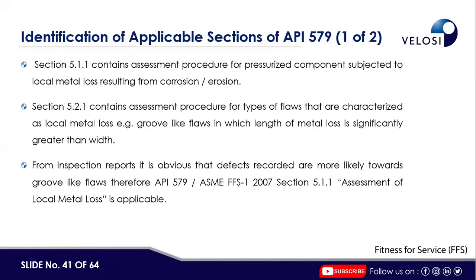So now, identification of applicable sections of API 579. Section 5.1.1 contains the assessment procedure for pressurized components subject to local metal loss resulting from corrosion or erosion. Section 5.2.1 contains the assessment procedure for types of flaws that are characterized as local metal loss, groove-like flaws in which the length of the metal loss is significantly greater than the width. From the inspection report, it is obvious that the defects recorded are more likely groove-like flaws. Therefore, API 579 section 5.1.1 assessment of local metal loss is applicable. That decision was drawn basically.